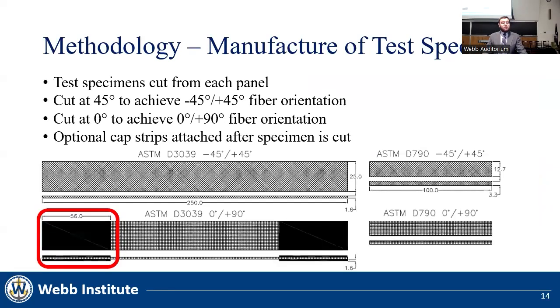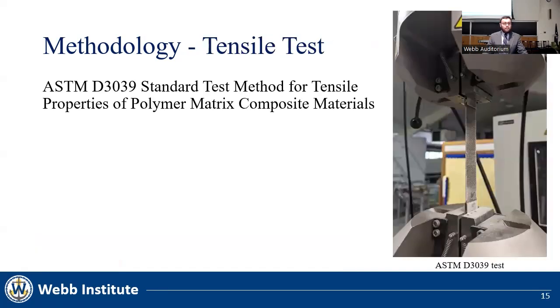Some were also cut at 0 degrees to achieve a 0 degree, 90 degree fiber orientation, where optional cap strips are utilized to reduce stress concentrations caused by the tensile test grips due to the higher tensile strength of this fiber orientation. The tensile test I utilized was the ASTM D3039 standard test method for tensile properties of polymer matrix composite materials, as can be seen in this picture.